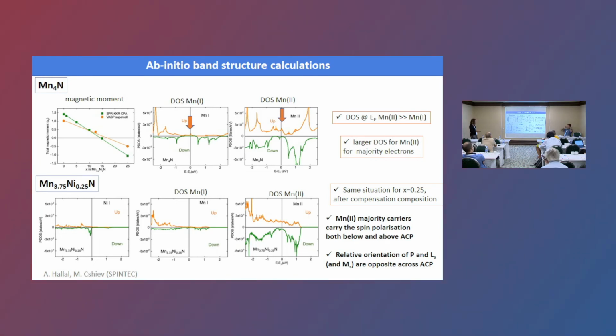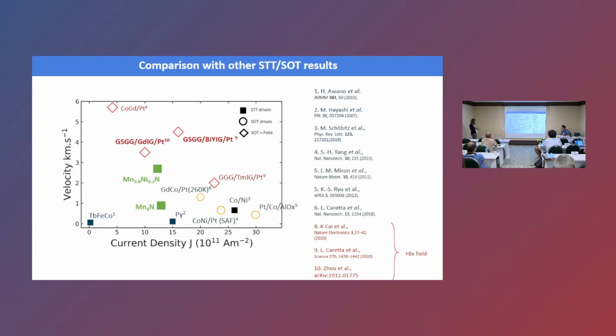the majority carriers in the manganese 2 sublattice were carrying the spin polarization both above and below the compensation. So this proves that the spin polarization doesn't change sign as the nickel composition is increased, and this can explain our result. The relative orientation of polarization and magnetization across the compensation explains the variation of the domain wall velocity direction while crossing the compensation. So I think it's finished.